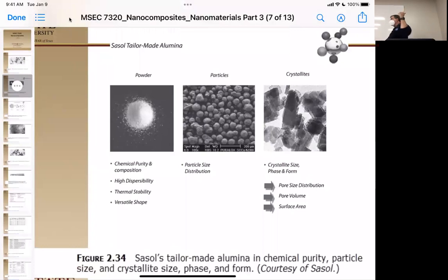So they are taking it and heating it up with water under pressure, and then it either creates an amorphous material, which is the spray version, usually amorphous because of the time scale. The hydrothermal process tends to make more crystalline materials because it has more time to form. But then once you have that, you are going to do the same kind of thing you would do with graphite, in that you take raw graphite, which is a bunch of little sections of platelets, grind that up till you get to smaller sections that are tactoids, and then you can process them from there.